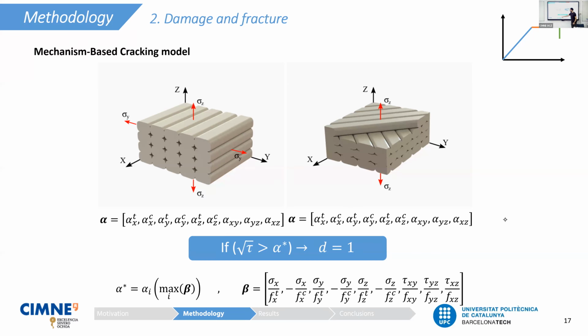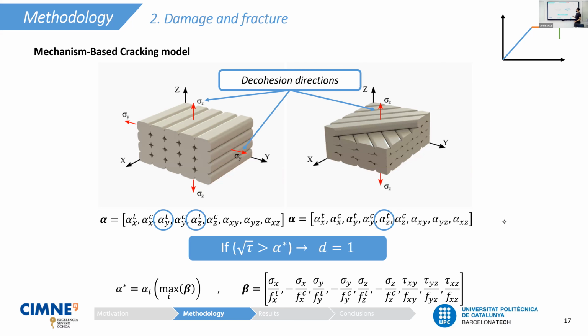And in this beta array, the component that is the highest one, the maximum component, meaning the direction or the failure mode that is under the highest solicitation, we are selecting that alpha value over here. These alpha arrays are basically material parameters, and those alpha that correspond to the decohesion, let's say to weaker strengths that we already know. For example, in the case of the aligned filaments, the Z and the Y directions are weaker directions, are brittle fracture. Those parameters will be much lower than the rest of the parameters.